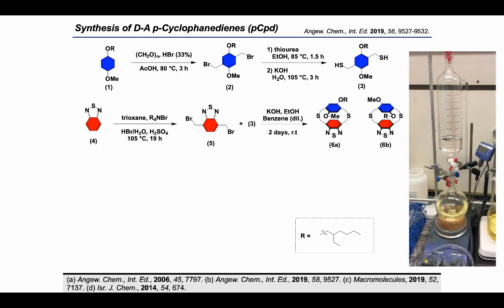Now we combine and dissolve molecules 3 and 5 in benzene in an addition funnel as shown on the right. We slowly added this to a dilute solution of potassium hydroxide and ethanol. It is important to add this slowly, usually over at least 2 days, to maximize the dilution of the reactants to favor an intramolecular cyclization reaction.